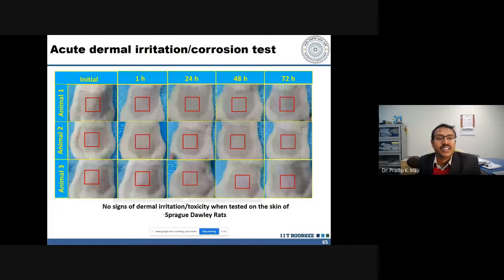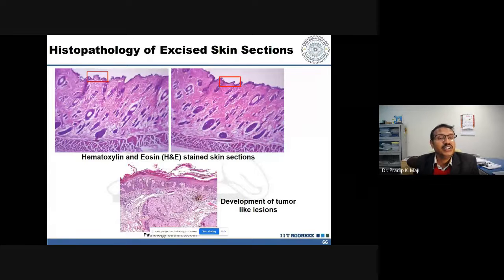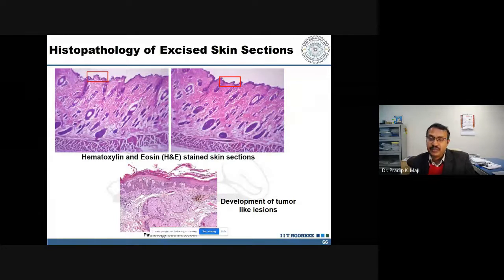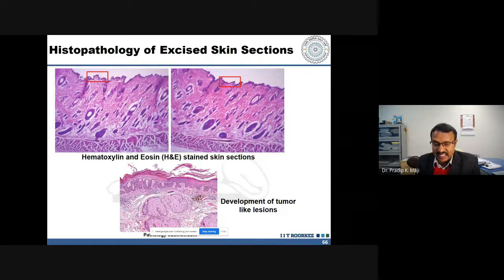And we have checked the acute dermal irritation corrosion test with a rat model. After 72 hours, we have seen there is no irritation after a thin layer coating of our material. Moreover, we have checked the histopathology of the excised skin section, and we have seen there is no change and no generation of tumor cells in the rats. So what I want to conclude from here is that our material is really good to utilize for biomedical applications, and we are working on it, and hopefully we can make it a very good stabilized property available in the market itself.